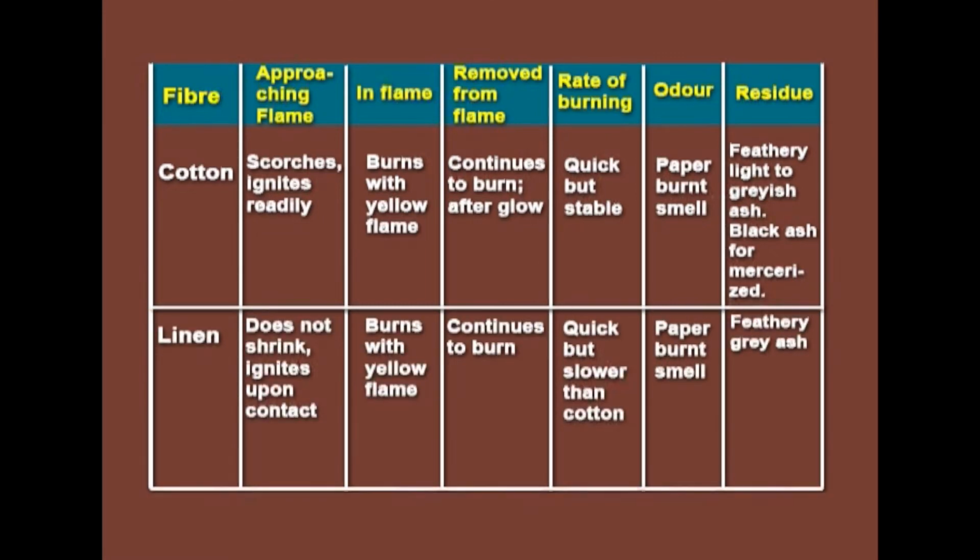If you take a linen fiber, it does not shrink, but it ignites upon contact and it burns with a yellow flame, and it continues to burn even after removing from flame, and the rate of burning is quick, but it is definitely slower than cotton, and it gives a paper burnt smell again, and it gives feathery grey ash.